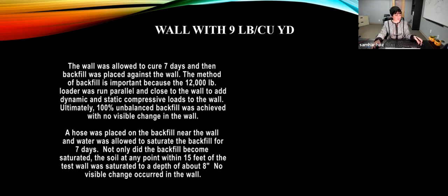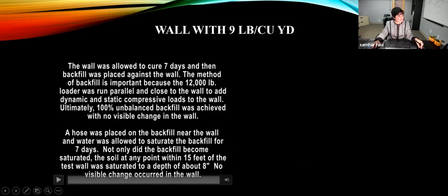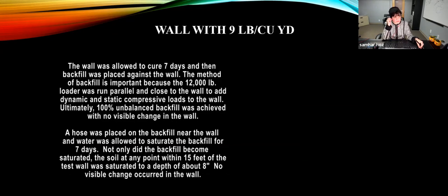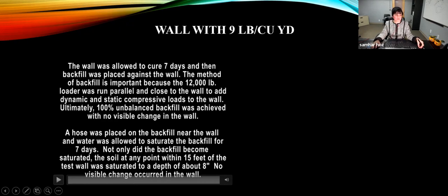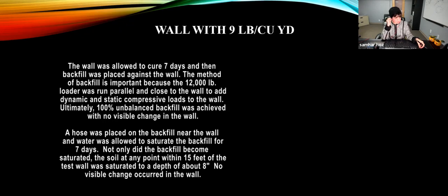Let me show you here. This is just a quick test. The wall was allowed to cure for 7 days, and then backfill was placed against the wall. The backfill is important because a 12,000 pound loader was run parallel and close to the wall to apply dynamic and static compressive loads. Water was allowed to saturate the backfill for 7 days. Not only did the backfill become saturated, the soil at any point within 15 feet of the wall was saturated to a depth of about 8 inches, and no visible change occurred in the wall.